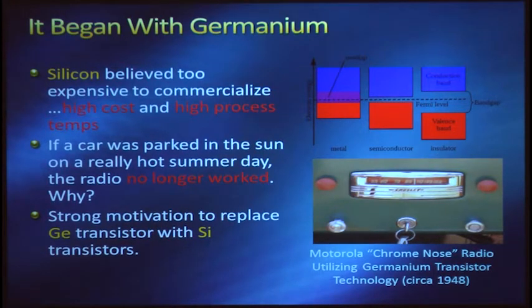But early on, in the devices made from germanium, a very interesting phenomenon happened where if you were in your car and you wanted to listen to the radio and you left your car parked in the sun and you came back to it, the radio no longer worked. And that's because semiconductors are in between a metal and an insulator. If we think a metal is always conducting, we can say it's always on. An insulator is very tough to put conduction through or put electrons through, so it's generally off. Semiconductors can switch, and when we dope these materials, we're able to make it better electronically conducting. So there was a strong motivation early on to replace these germanium-based transistors with silicon ones.